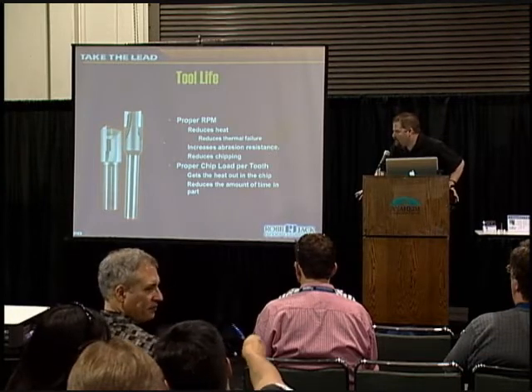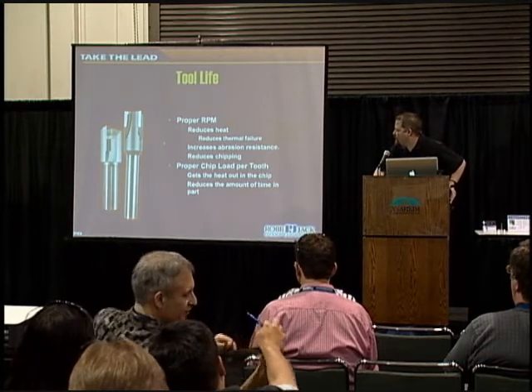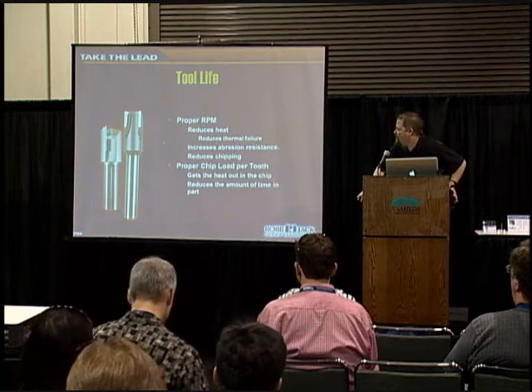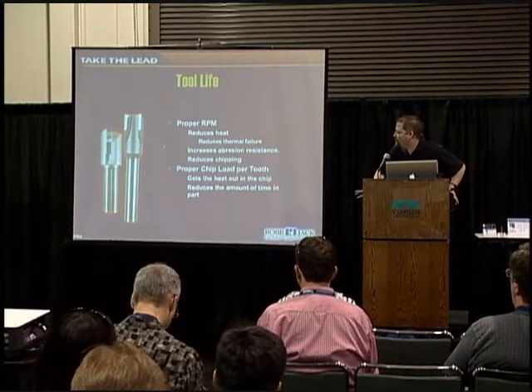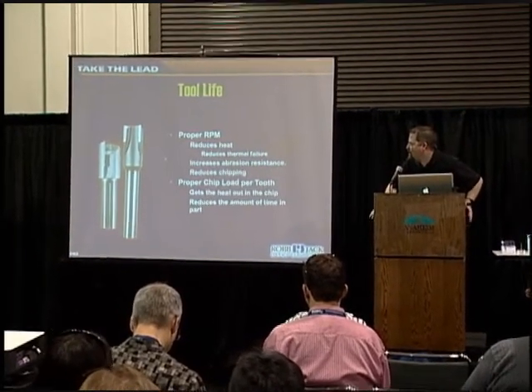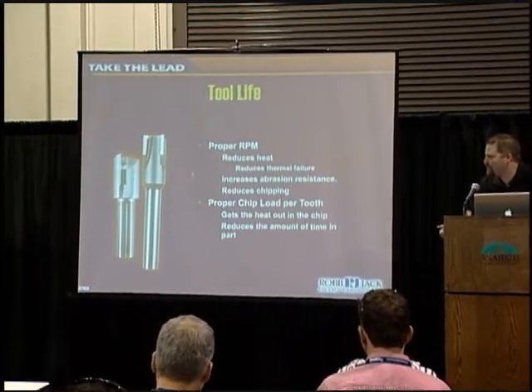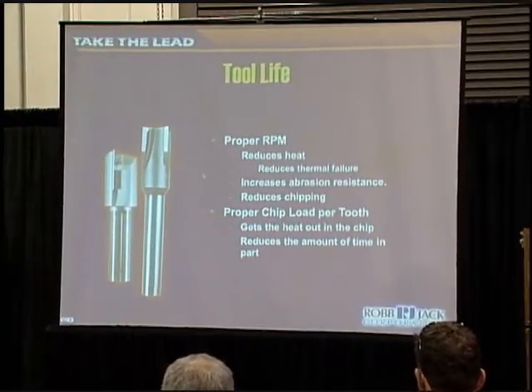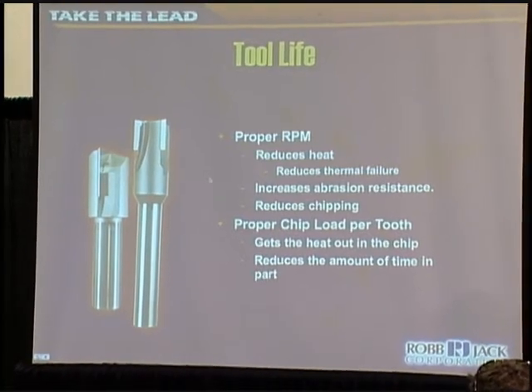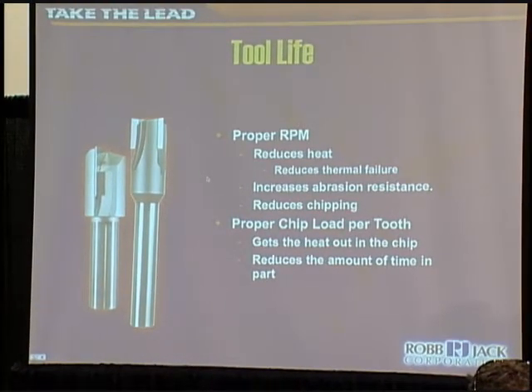On the troubleshooting side and proper tool life, I mentioned it before, you want to go not too high of an RPM, and you want to go a very fast feed rate so that your chip load is up so you don't build up heat. You want to get into the part and out of it as fast as you can. So that 3/8 tool that you saw had a 6 thousandths chip load and was running at about 10,000 RPM.